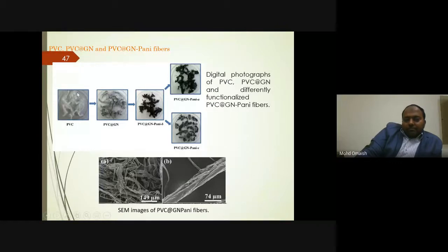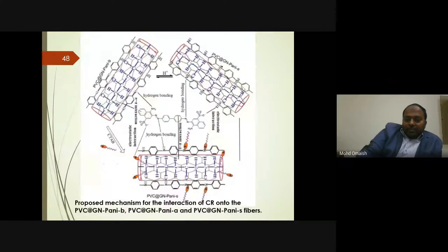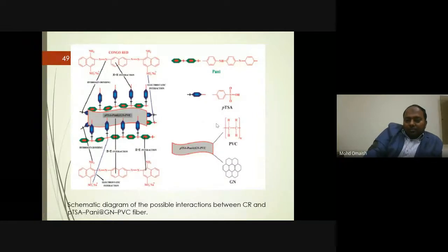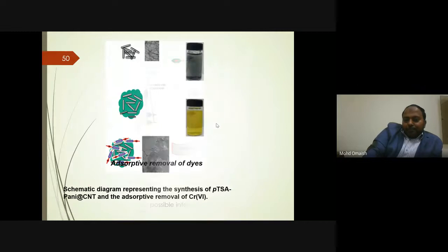This is very simple work. Here we simply made polyvinyl chloride fibers and functionalized them with polyaniline. This was done by just mixing polyaniline and PVC solution in water under very high stirring. We got very good adsorption results, associated with the functional groups of polyaniline that were responsible. This is also one of the mechanisms for the adsorption. This is one of our papers where we used a polyaniline composite for the adsorptive removal of dyes. Here we can see the adsorption of dye, and in the end we get a very good colorless sample.